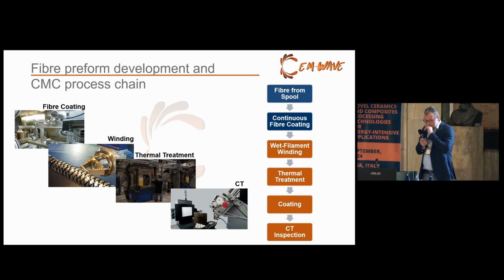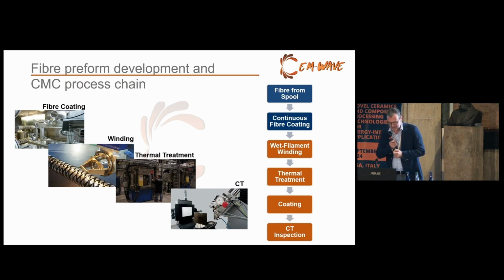Again, we saw it already. It's also the reason why CMC are so important, because you have a long way to go from the fiber to the ready ceramic matrix composite. Even here, you have the fiber from the spool, which you get. Then you have to fiber coat it, and you have to coat it so that you still can use the fiber for the filament winding. It does not make sense when you coat your roving, and then you cannot take it out from one another. You cannot filament wind, so this is not so easy to do.